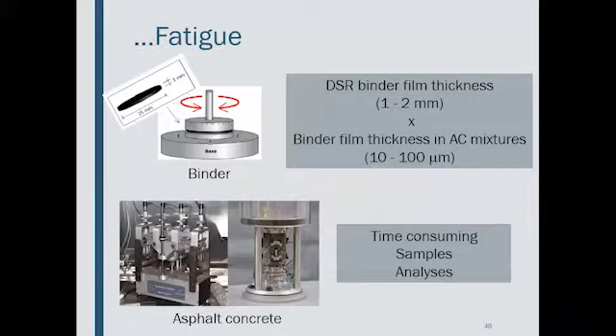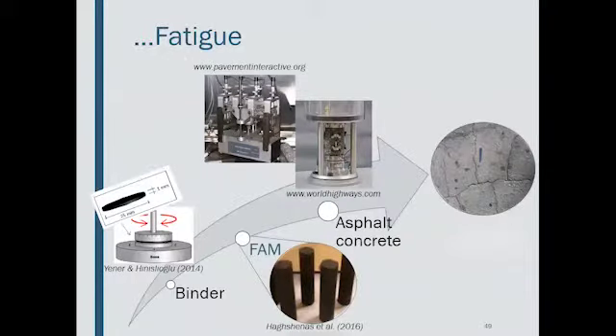But when we see the results for the binder test, we can note some problems because of the difference between the film thickness in this test and the real film thickness that exists in the asphalt concrete. And in the other scale, you have good results, but it's time consuming, it's hard to get the samples, and the analysis can be complex. Then we can try to work at an intermediate scale. Many studies have shown that it's possible to work with them to predict this mechanical behavior.